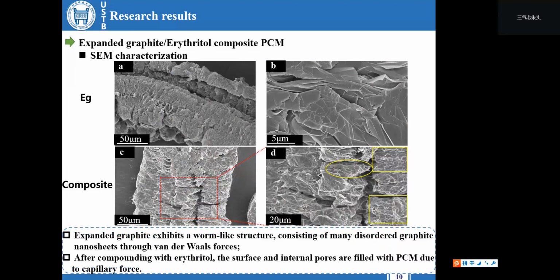By SEM, the microscopic morphology of the expanded graphite raw material and the 5% expanded graphite erythritol composite phase-changing material was characterized. From figures A and B, it can be observed that the expanded graphite exhibits a worm-like structure, which is connected by a large number of disordered graphite nanosheets through van der Waals forces. After the expanded graphite is compounded with erythritol, its surface and internal pores are filled with the phase-changing material due to the capillary force, and the phase-changing material is successfully loaded.